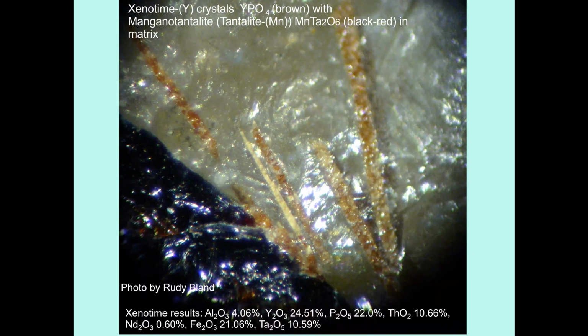Note the chemical composition of the mineral, which is yttrium phosphate, and compare it with the EDS test results, which show a little bit of aluminum, yttrium, phosphorus, some thorium, neodymium, iron, and tantalum. This illustrates why the more abundant of the rare earth minerals, most notably monazite-Ce, are such important sources of all the elements in this group, which are used extensively in high-tech industries. Next slide.